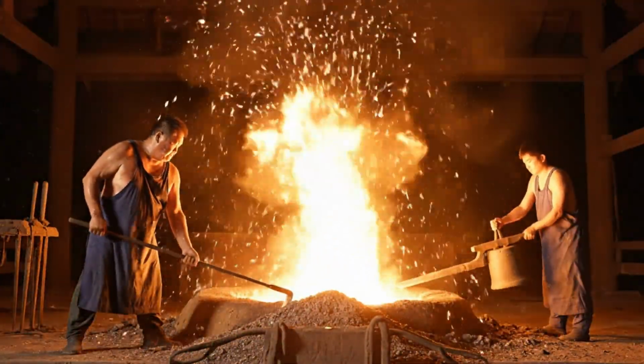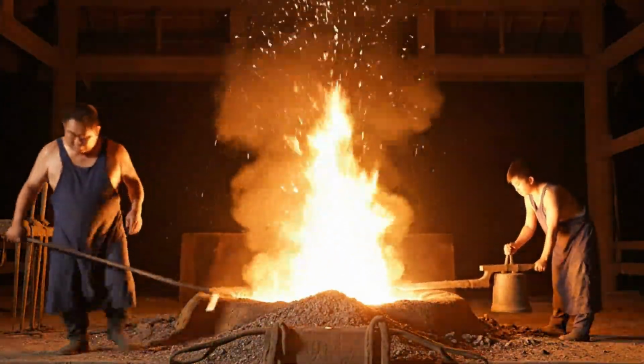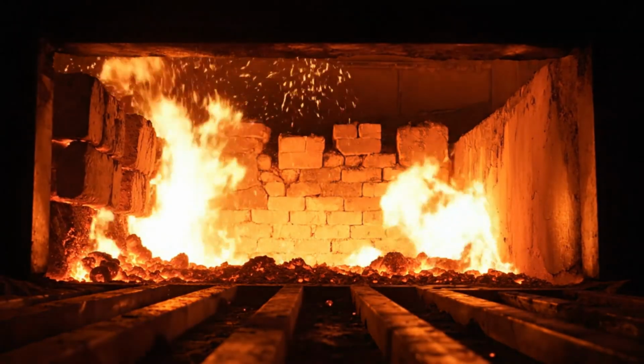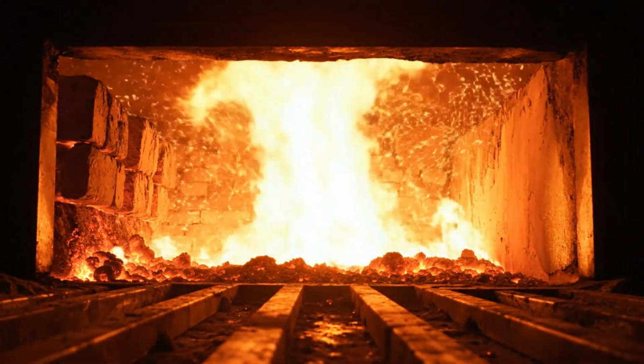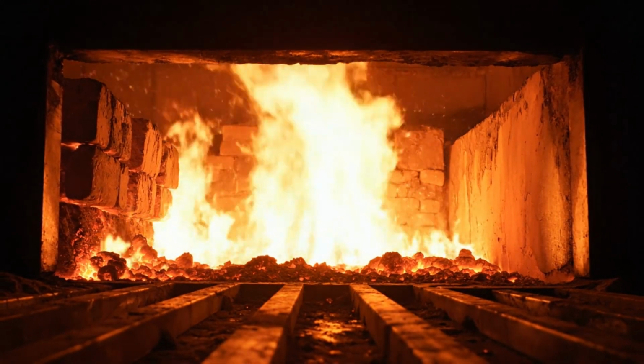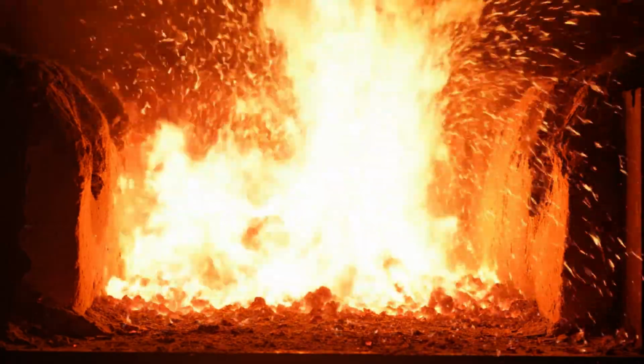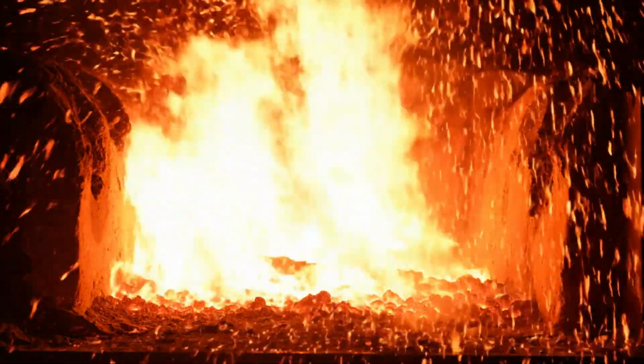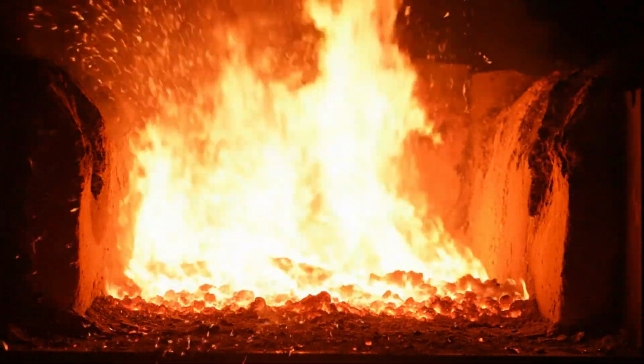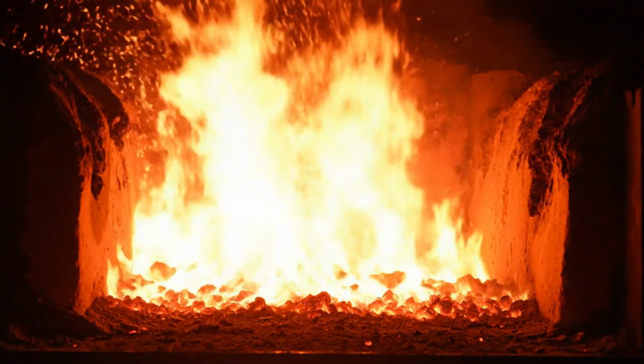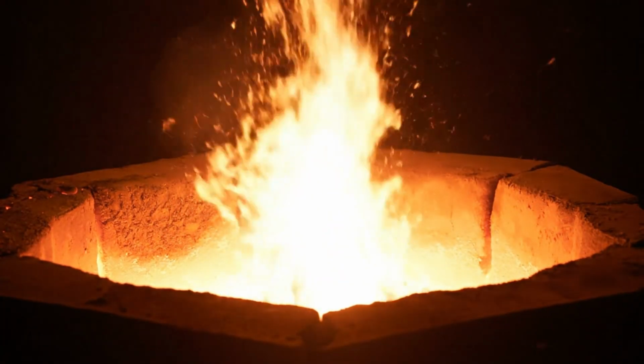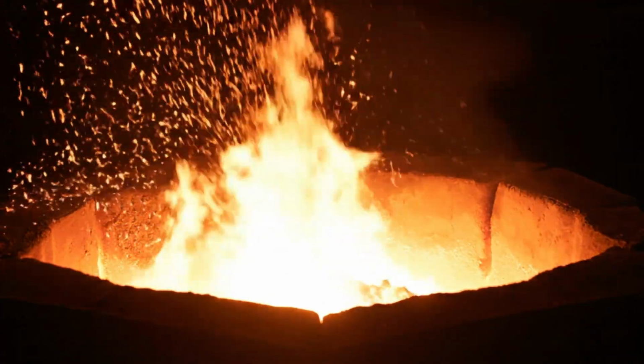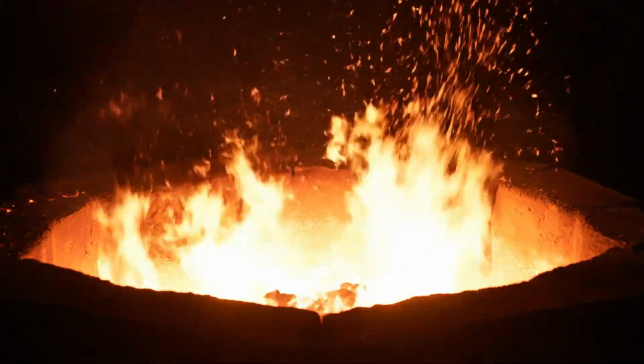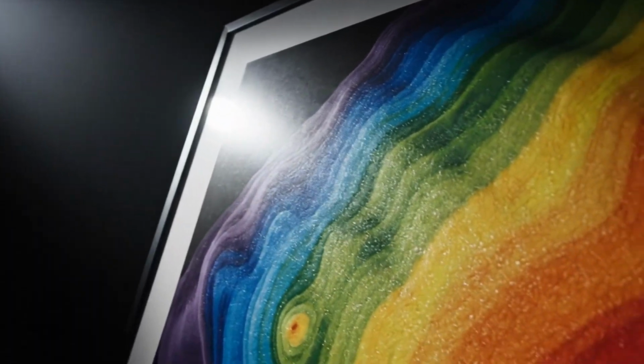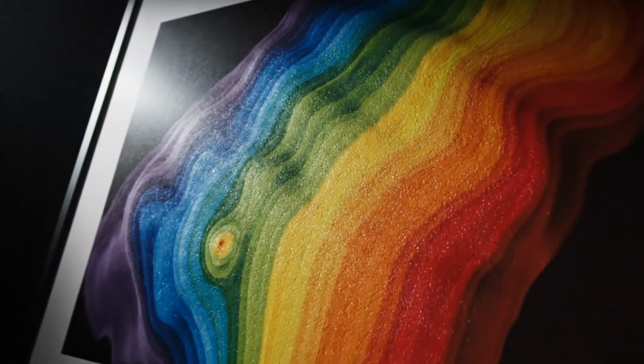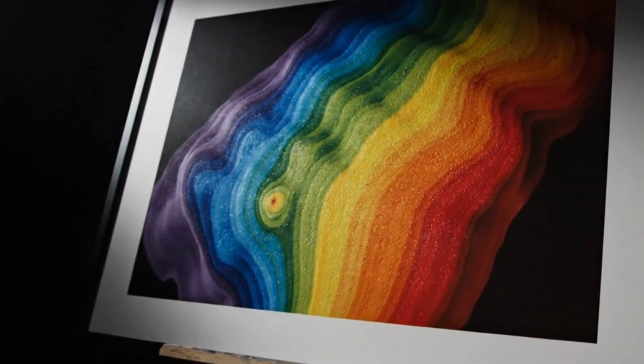The role of charcoal here is almost universally misunderstood in popular discussions, and the misunderstanding leads to a fundamental confusion about what the process actually achieves. Charcoal is not simply a fuel that generates heat. It is a reducing agent. As it burns, it produces carbon monoxide, and that carbon monoxide reacts with the iron oxides present in the satetsu sand, stripping away the oxygen that keeps the iron locked in its mineral form. What remains is metallic iron. At the same time, some of the carbon itself is absorbed into the iron at varying rates, depending on local temperature position within the furnace and the flow of air from the bellows.